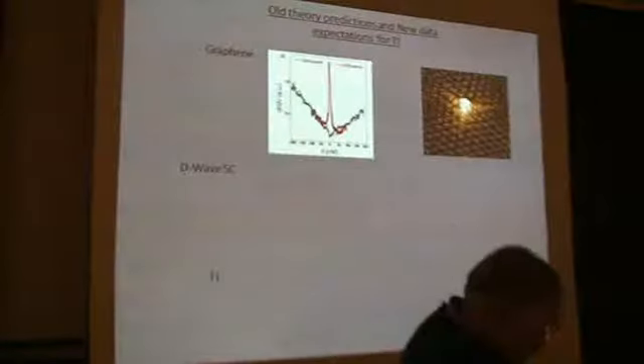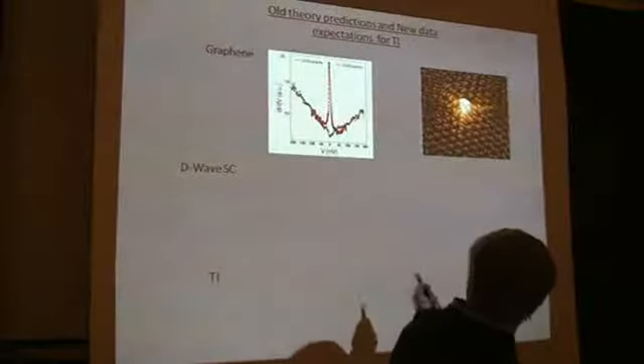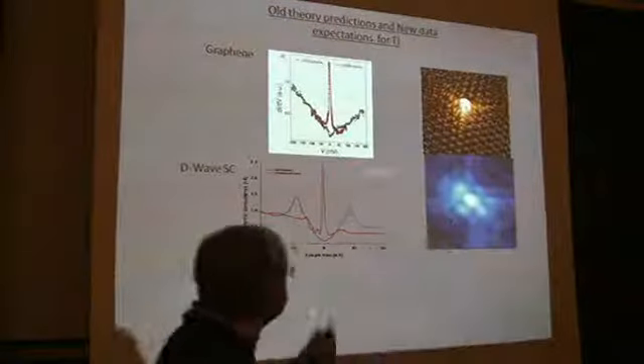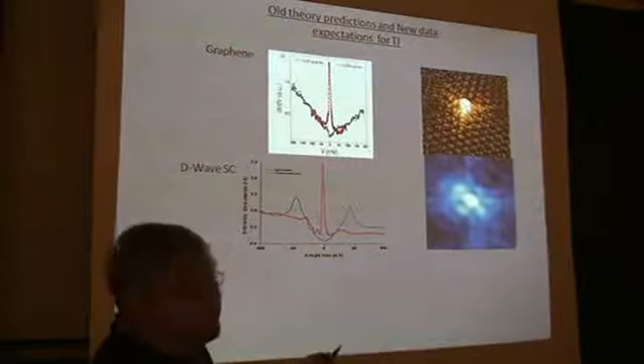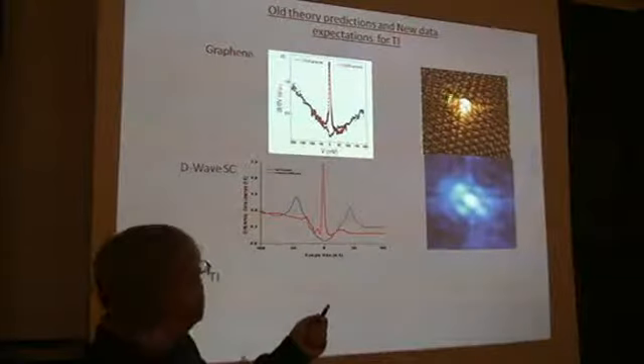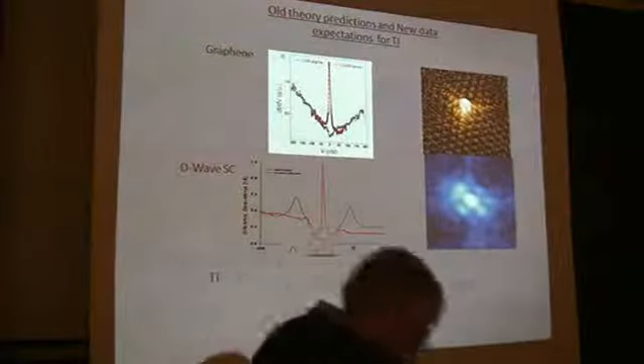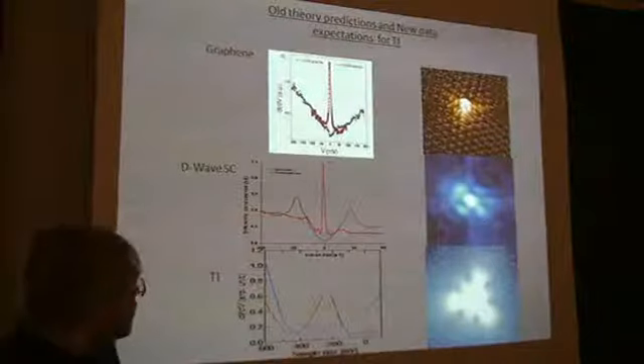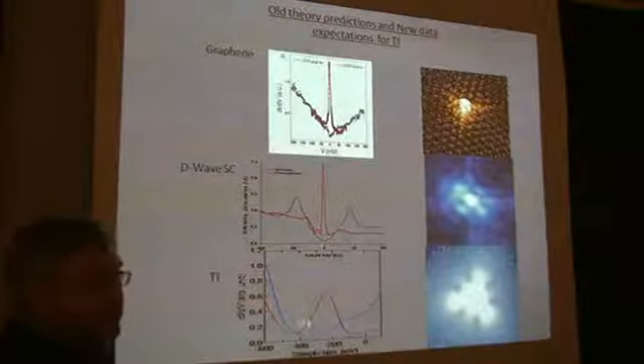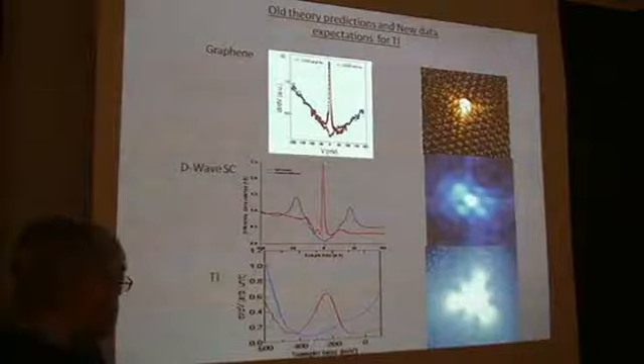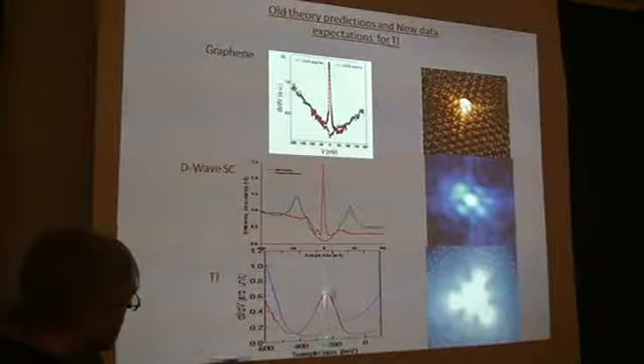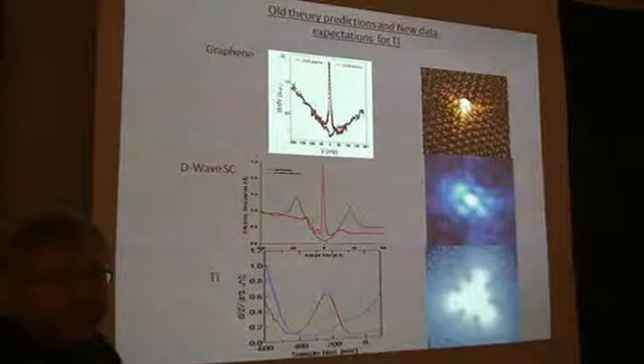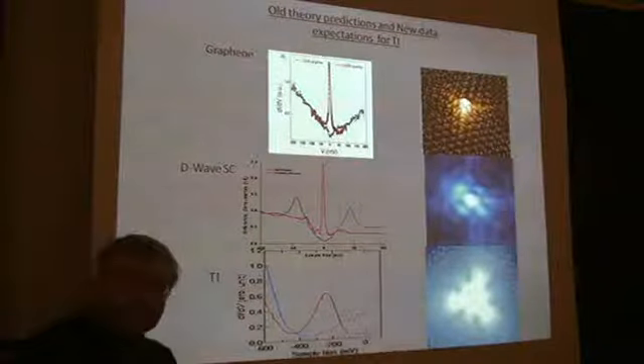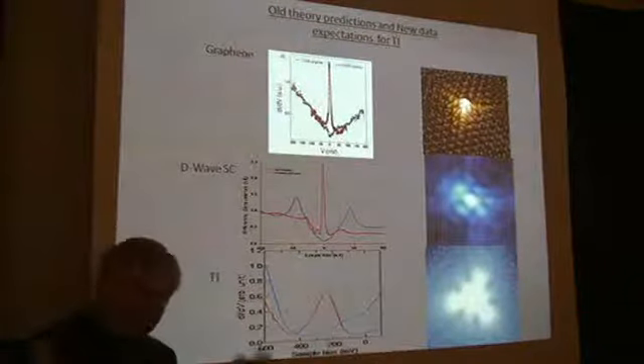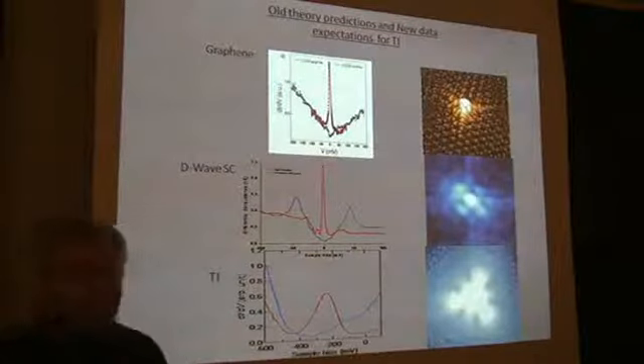So let me show you then, as a message. Here is actually what happened in graphene, the pristine case with impurity-induced resonance. Here is what happened for D-wave. Obviously there is a big difference. This is four-fold coordinated, this is a square lattice, this is honeycomb. So let me show you something for a topological insulator. This is a topological insulator, and this is unpublished data. Maybe this peak will get sharper. It is possible that this peak is due to iron or a magnetic impurity. But all I'm saying, in addition to the discussion so far, is that there are some intragap or inside the Dirac cone resonances induced by impurity scattering.